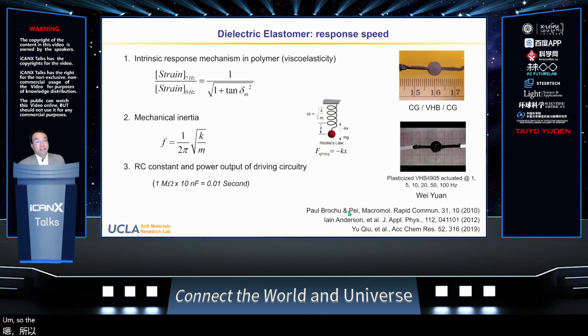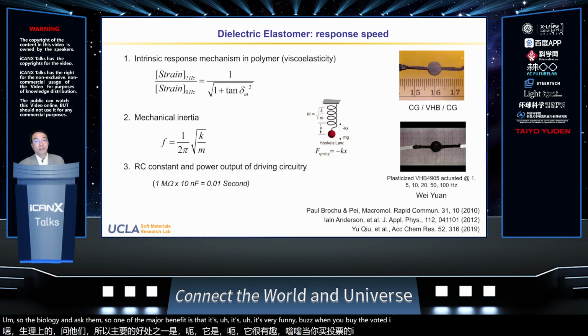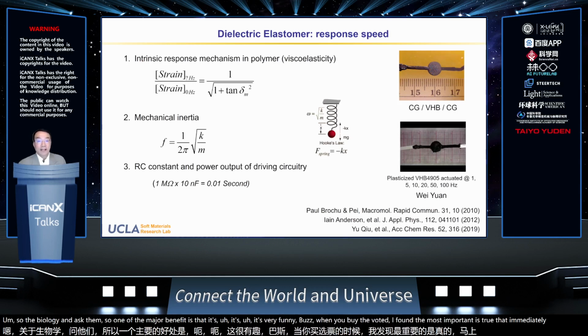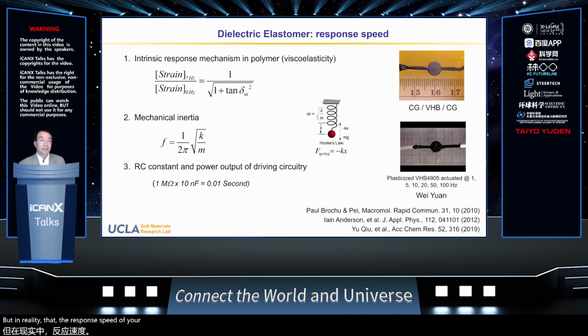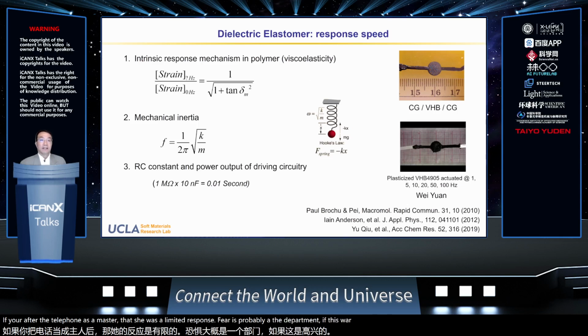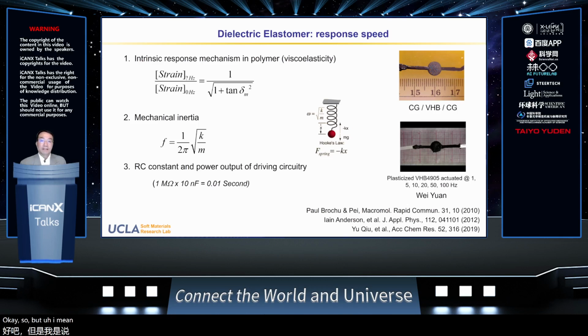So one of the major benefits of the dielectric elastomer is that the response is fast. When you apply the voltage, it expands; remove the voltage, it shrinks back immediately. But in reality, the response speed of your actual actuator or device will depend on a number of different factors. The first that comes to mind is the viscoelasticity. Most of the time, if your dielectric elastomer actuator shows a limited response speed, it's probably because the polymer is viscoelastic.